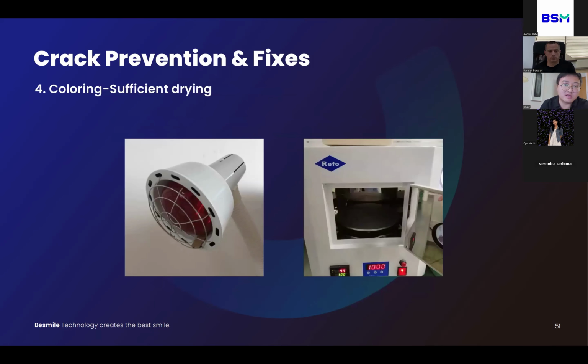And next part is about the coloring. If you use 3D Master, if you use multi-layer blocks, generally you don't need to do the internal coloring. But if you use the precious blanks, white blanks, you have to do the coloring before sintering. After we do the coloring, we have to dry the restoration. If we don't dry the restoration for enough time under enough temperature, the risk of the crack will be much higher because the residual coloring liquid will influence the shrinkage and the transformation. So to avoid this problem, we need to make sure the drying time is enough.